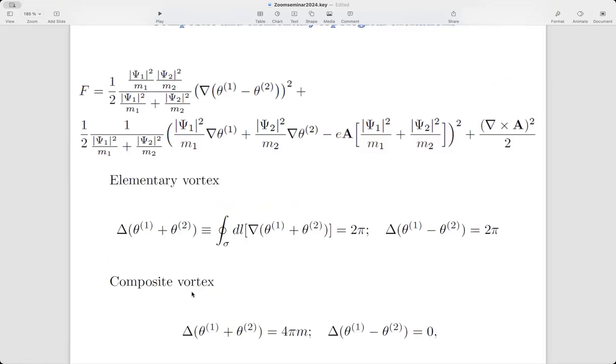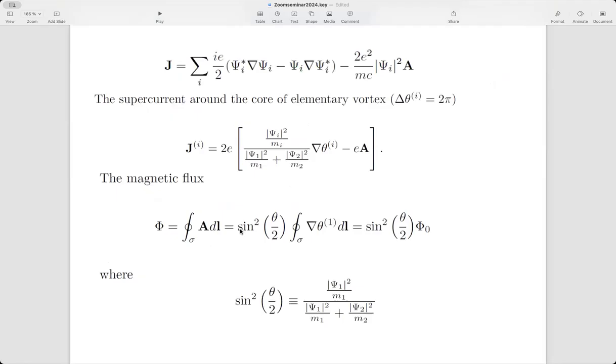So let us look now at an elementary vortex, meaning a vortex where only one phase winds by 2 pi. And then one can write the most standard equation for supercurrent, just standard London-Ginzburg-Landau. And then one calculates the supercurrent of a vortex with phase winding only in component 1. There is only one phase gradient in such a case, and so only one of these terms has a phase winding. We retain only, let's say, component 1.